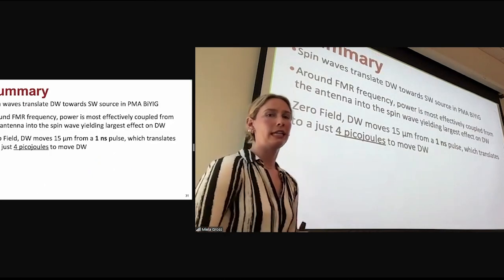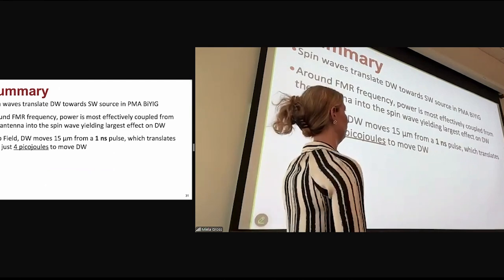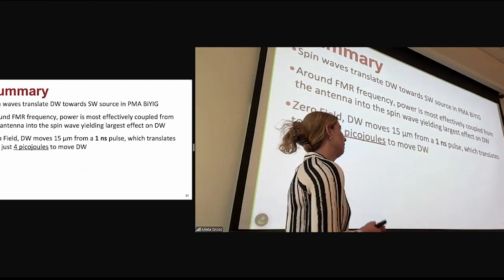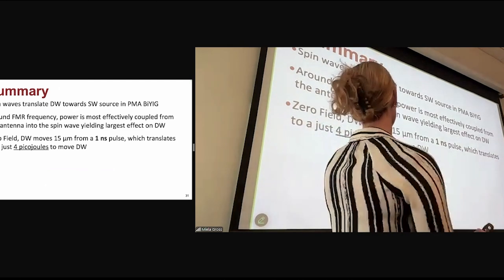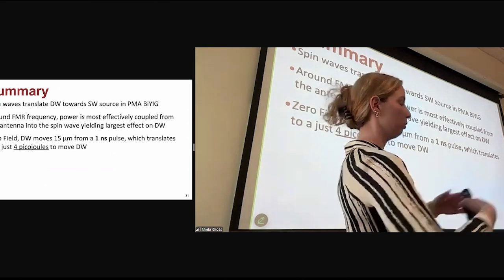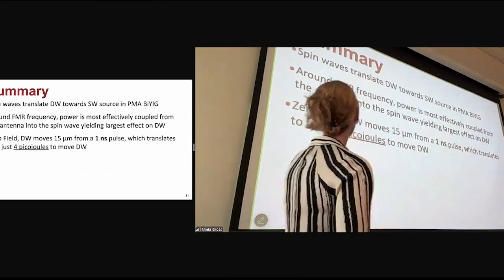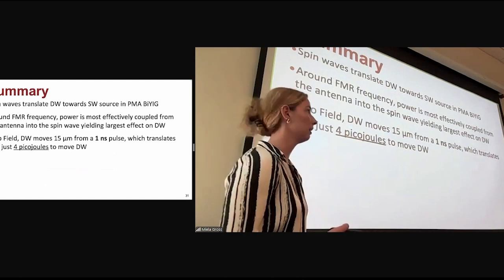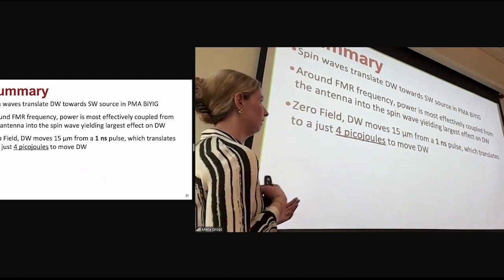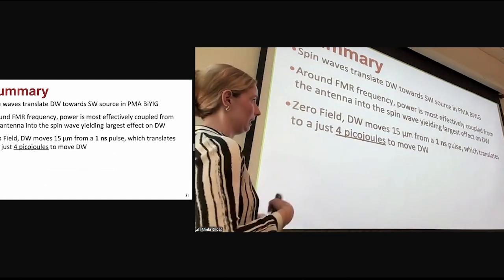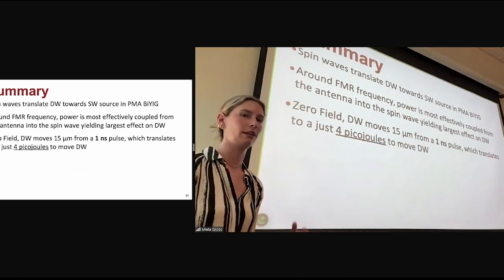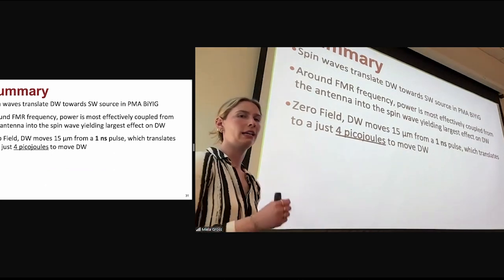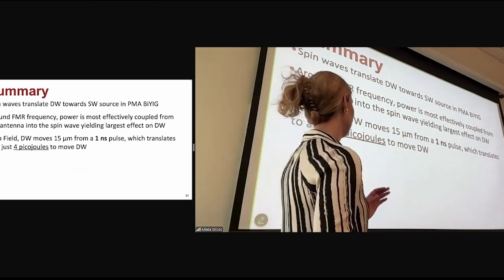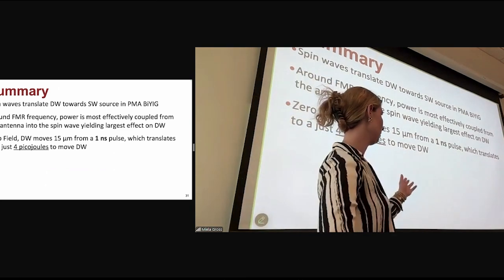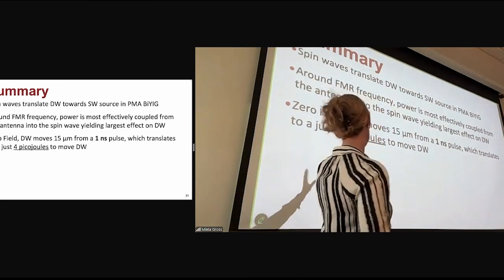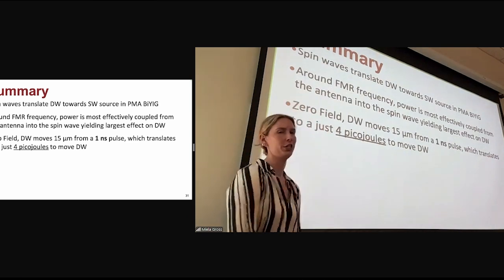So in summary, we have demonstrated spin wave induced domain wall motion in our PMA bismuth-YIG, showing that the spin waves translate the domain wall towards the spin wave source. Around FMR frequency, we see the power of the RF pulse is most effectively coupled from the antenna to the spin waves, yielding the largest effects on the domain wall. And at zero field, we see the domain wall move 15 microns from a 1 nanosecond pulse, which again translates to just those 4 picojoules of spin wave energy.